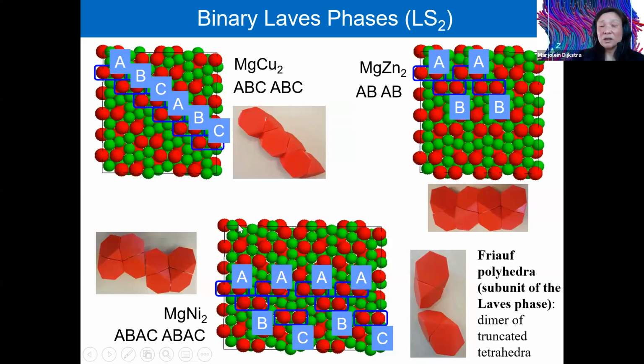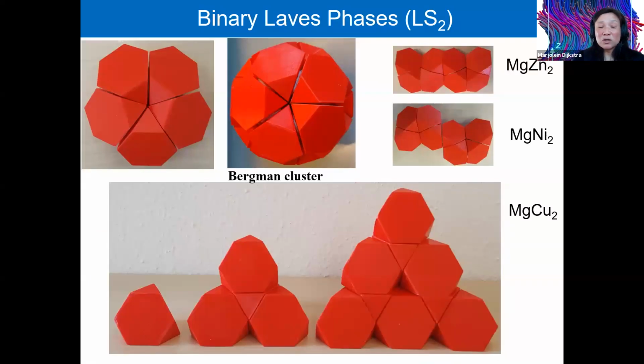in an AB-AC fashion. And so if you want to grow bigger tetrahedral domains, this is only possible if you have a magnesium copper phase. And so that's the reason why it turns from the more stable magnesium zinc phase in the bulk towards a magnesium copper phase when you confine these particles inside a bigger sphere.